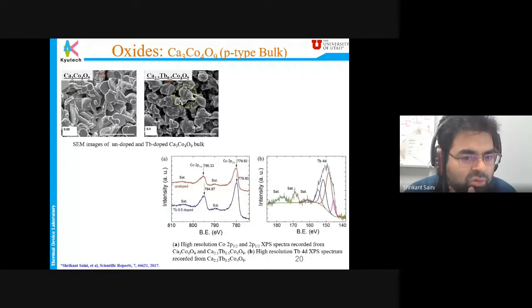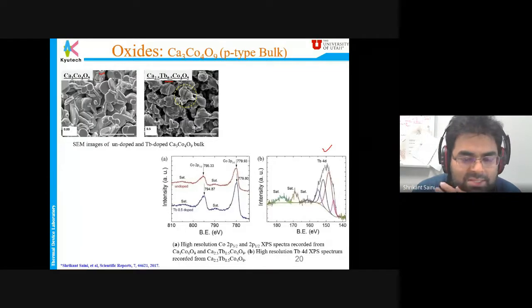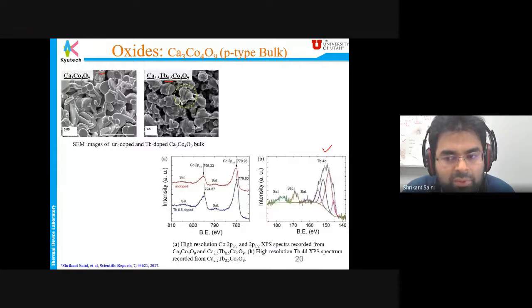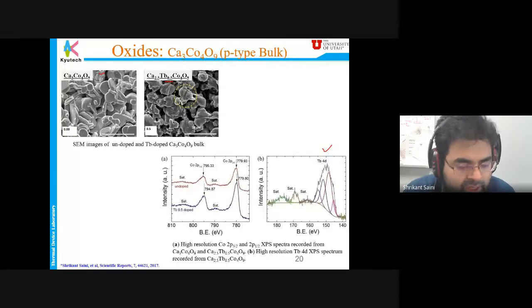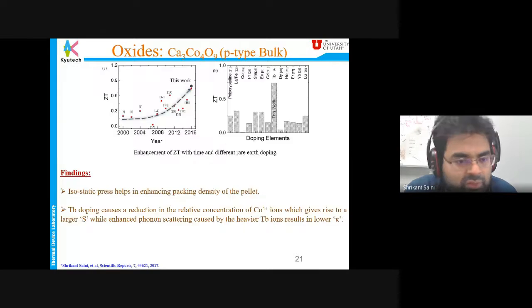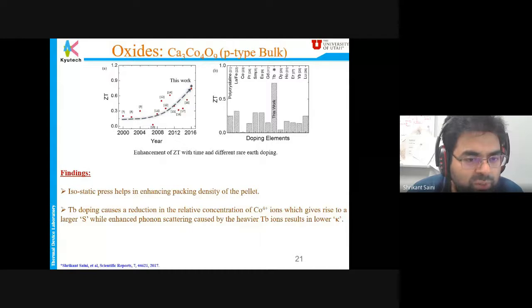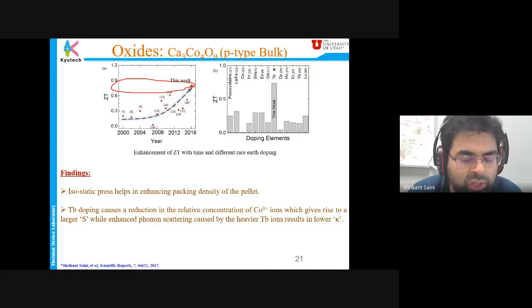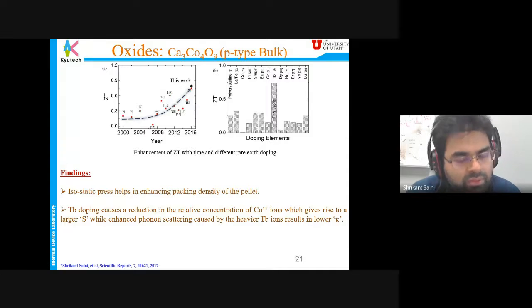What we see here is a layered structure which shows the presence of the terbium ion. The presence of the terbium ion helps us to increase the carrier concentration, which we will be seeing in the next lessons. When we work on that material, what we found is ZT increases and reaches around 0.75, if I'm not mistaken. This is the best reported material for P-type as a bulk material, with ZT around 0.75 or 0.8. I think this is still the best work. Nobody has reported more than this ZT yet.